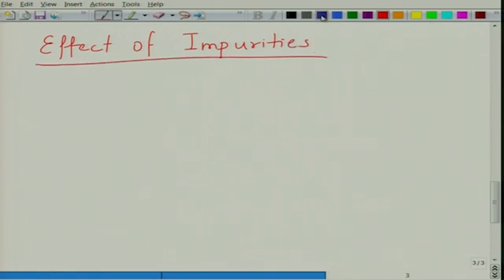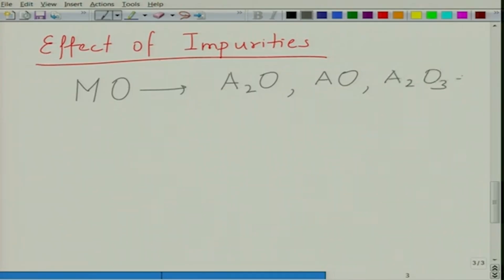Now, let us look at another case which happens in oxides, which contributes to defect chemistry in a very significant way, that is effect of impurities. And the reason for that is because nothing is pure in nature. Okay. Thermodynamics itself prefers the impurities, and as a result there are always impurities present. So, if you have oxide MO, you might have an impurity. Let us say I have an impurity which is A2O. Okay. I can have an impurity which is AO, I can have an impurity which is A2O3 in very small amounts, and these impurities could be either substitutional or they could be interstitial.